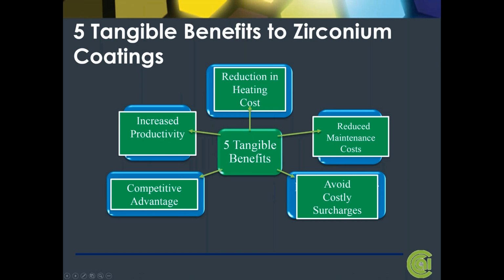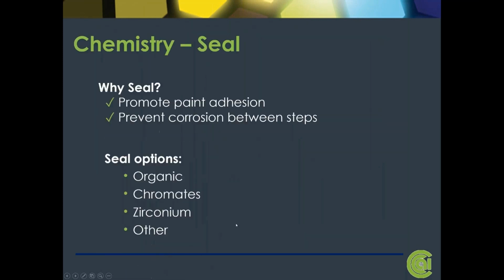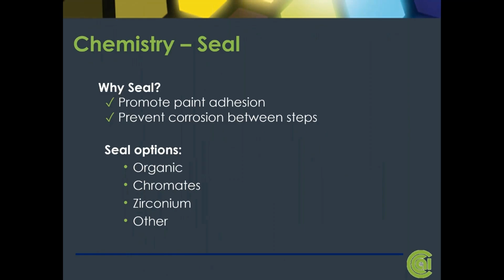Talk about the seal nets. Why would you use a seal in a pretreatment line? Typically, this is done to promote paint adhesion, especially after an iron phosphate. The military specs still require a chromate seal over zinc phosphates. There is a strong push to get away from this by the military. They're testing very aggressively to get away from this and move toward non-chrome or trichrome seals, but they are still being used. Iron phosphates require this to get better paint adhesion and corrosion protection.